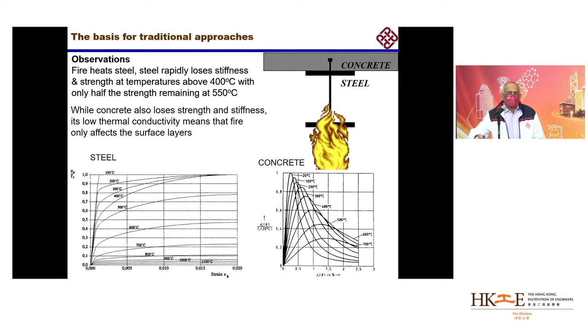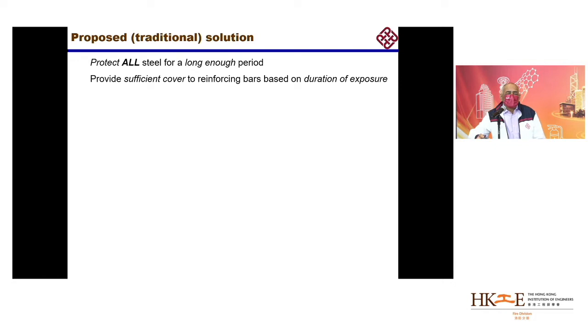Concrete also loses strength and stiffness, as the graph on the bottom left shows. But in the case of concrete, because it has much lower thermal conductivity compared to steel, it doesn't lose so much of its sectional strength and stiffness, because most of the heat is limited to the surface layers. So that's the general understanding of material behavior in fire.